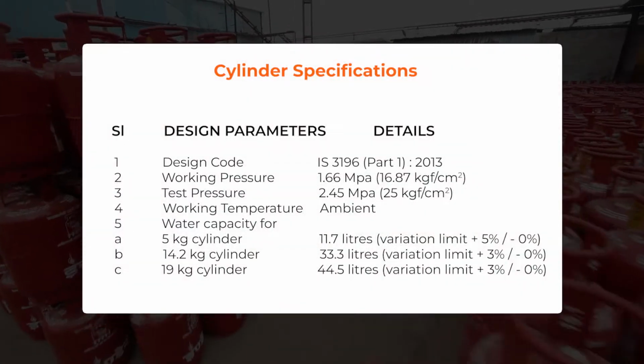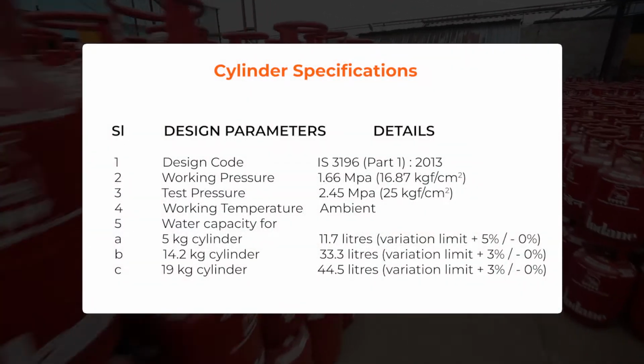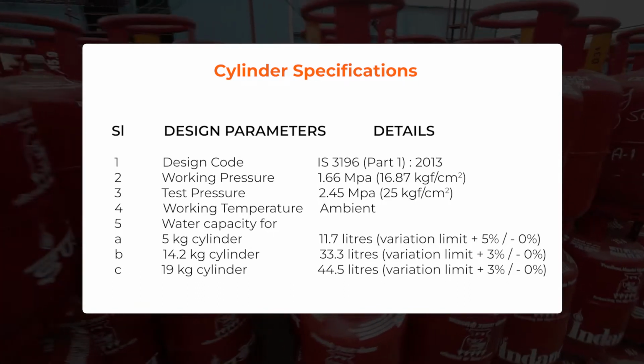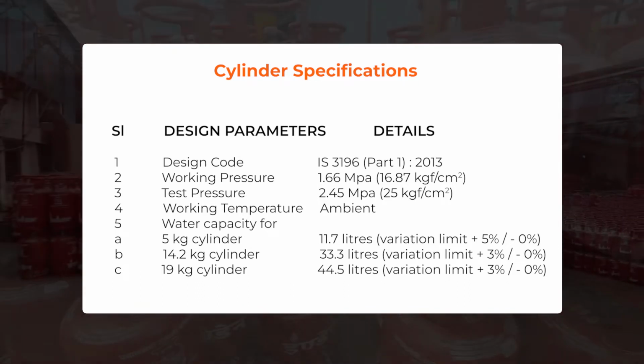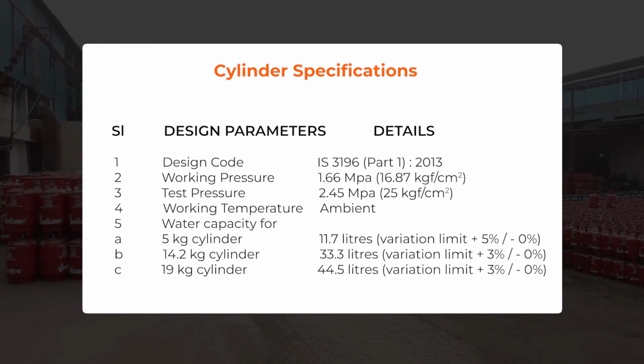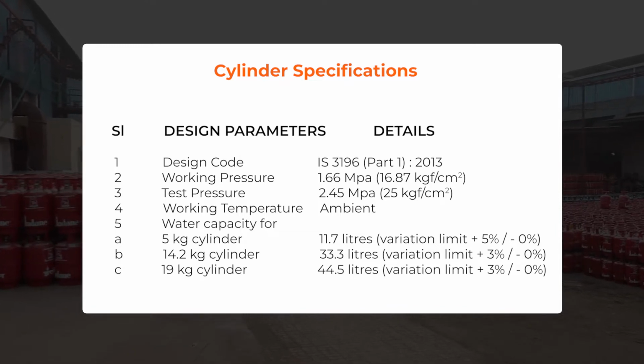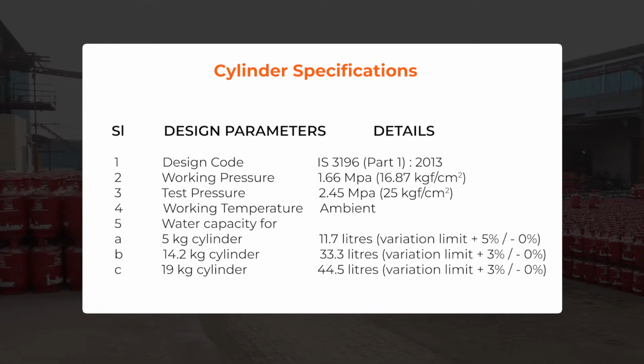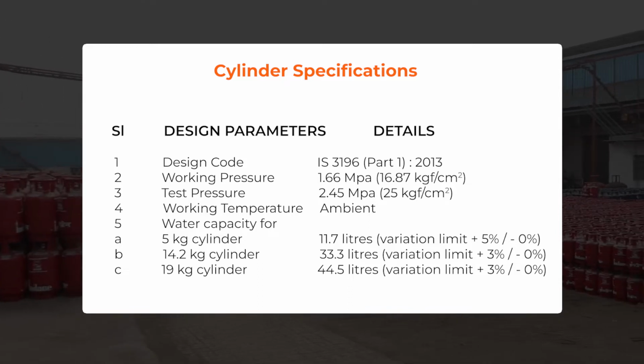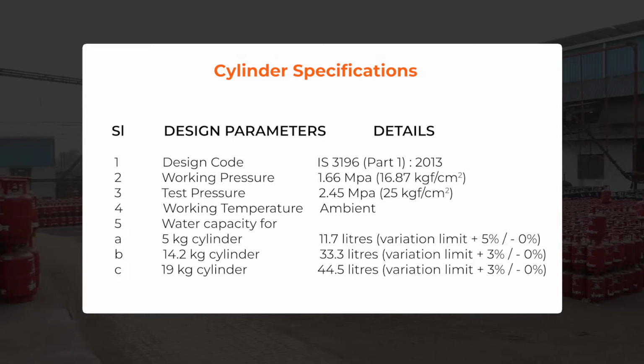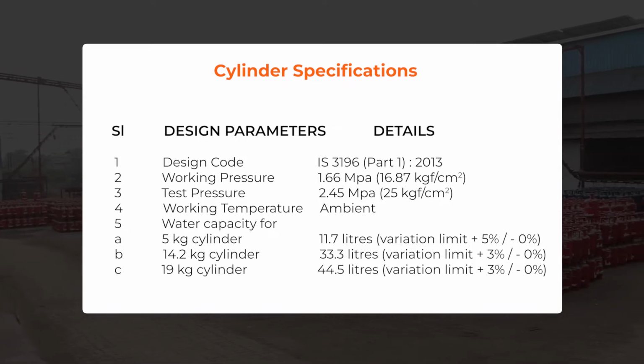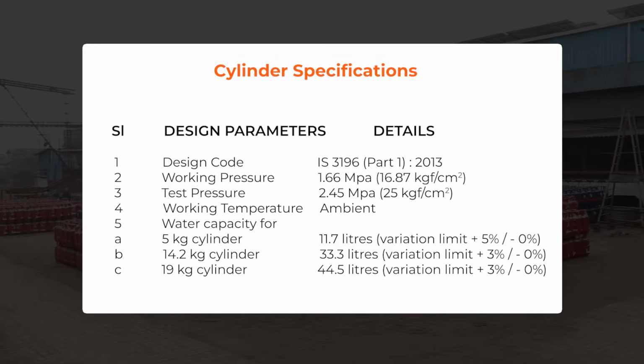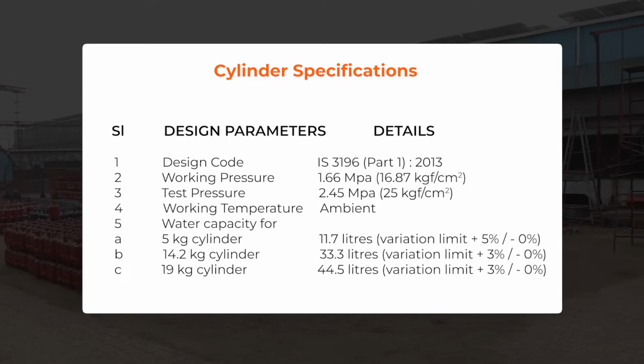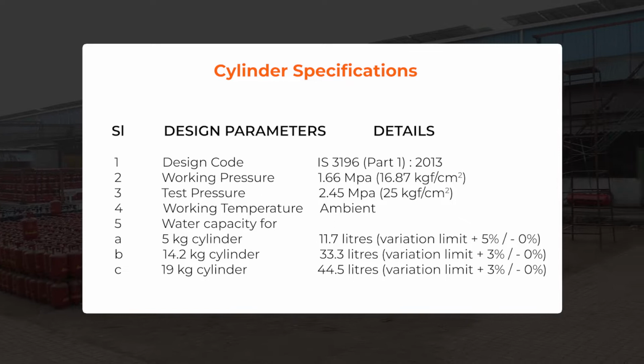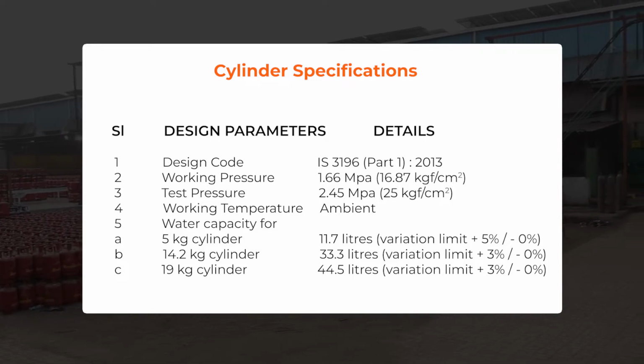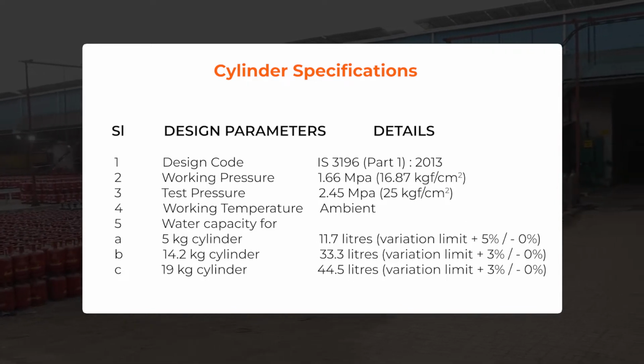The cylinder dimension and critical parameters are well defined in the system. Design code IS 3196 Part 1 2013. Working pressure 1.66 MPa, 16.87 kg force per square centimeter. Test pressure 2.45 MPa, 25 kg force per square centimeter. Working temperature ambient. Water capacity for a 5 kg cylinder 11.7 liters. Variation limit plus 5% to minus 0%.